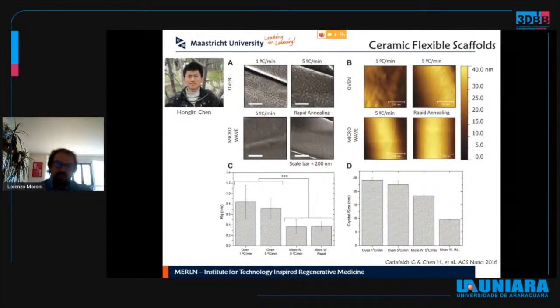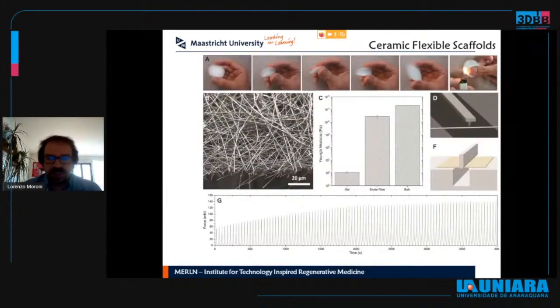So inspired by these two works, what we did with Honglin Chen, a former PhD student in the group, now a group leader back in China, was to spin a relatively bioinert ceramic material such as zirconia, and then, during the sintering phase, selectively change either the roughness or the crystal size of the formed nanofiber scaffolds. The first thing that was particularly interesting was that these electrospun mats seemed to be quite flexible, which for a ceramic material is quite unique. We also tried burning the material to see if this was due to some polymer remnants in the scaffold, but that was not the case.